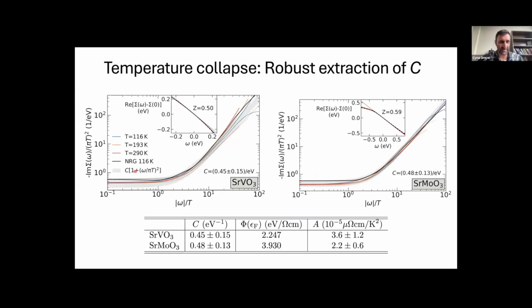So these are the results for strontium vanadate and strontium molybdate. These plots are a little bit busy, but they're plotting the same thing, the imaginary part of the self-energy over pi squared T squared versus omega over T. This is now for different temperatures and including the NRG data, which does not include the analytic continuation. You can see that the lines approximately collapse onto one curve, as they should for a Fermi-Liquid. We take the region of error to be the region spanned by these different curves. And same for strontium molybdate. From these calculations, we can robustly extract the C parameter and therefore the T squared parameter of the resistivity from the Fermi-Liquid scattering.